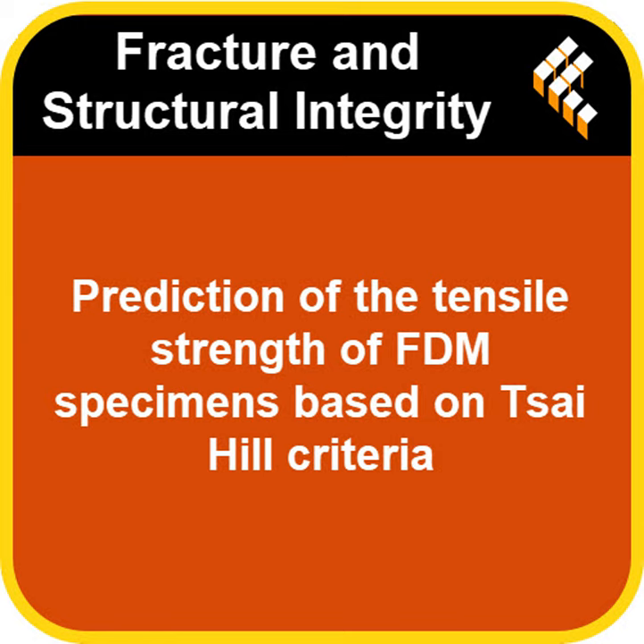So how did they use it here? What the researchers did was clever. They took the strength values they actually measured in some of the simpler tests, specifically the tensile strength at 0 degrees, the tensile strength at 90 degrees, and the shear strength measured on the 45-degree samples, and they plugged those numbers into the Tsai Hill equation to try and predict what the tensile strength would be at that trickier 45-degree angle. Oh, okay. So use easy measurements to predict a harder one. You got it. So if you're designing a part and you know it's going to see stress mainly at a 45-degree angle to your print lines, you could potentially run these other, perhaps easier, tests, 0 and 90 tensile, 45 shear, and use Tsai Hill to estimate how strong your part will be in that 45-degree direction without having to test that specific angle every single time.